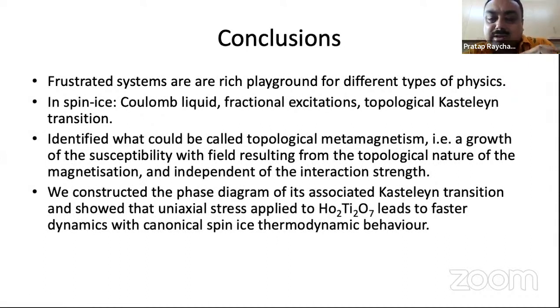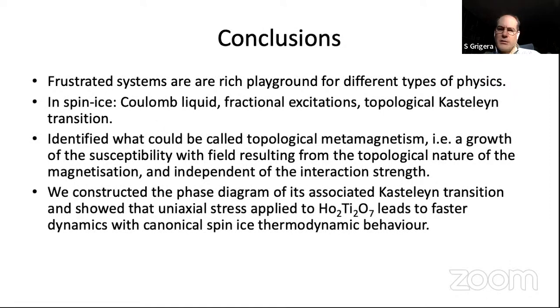So, tell me one thing. When you showed the specific heat, you don't recover the full entropy. Is that because the ground state has a large degeneracy and therefore the entropy at zero temperature is finite? Exactly. So essentially, if you assume that you're starting from 0, which would be the least biased assumption, then you integrate out and you see that you're missing something. So you say, okay, my assumption was wrong. What I'm missing here should be down there.